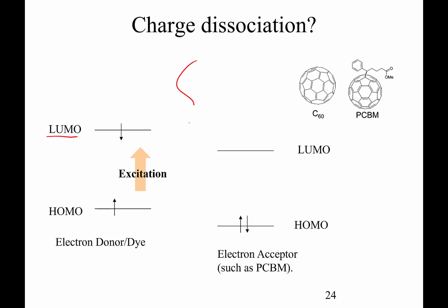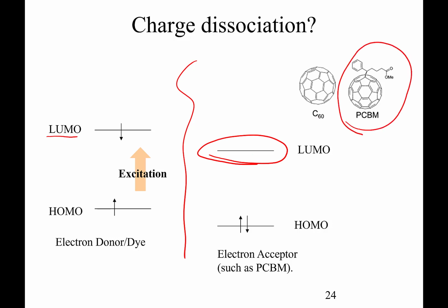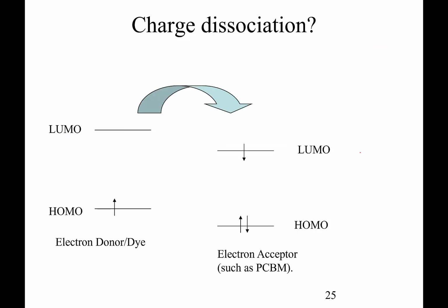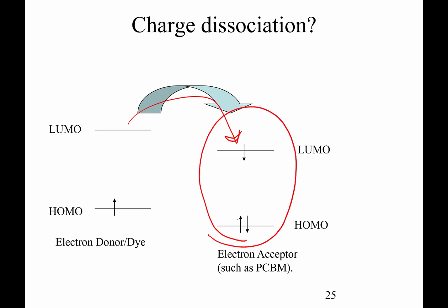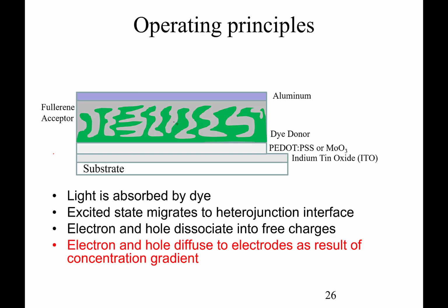And at that interface between these two materials, what happens is that electron will hop from one material over to the other. Why? Because the LUMO, in this particular case, the LUMO of the PCBM, these fullerenes, they love electrons. They have very low-lying LUMOs and HOMOs. So these LUMOs end up being a long way down, very low. And what happens is that electron sort of hops over here and stays in the LUMO of the fullerene. And this means that this fullerene now has an extra electron. So it would have a negative charge, and we're left with the hole, which is the absence of the electron on the left-hand side. So that's the importance of that interface.